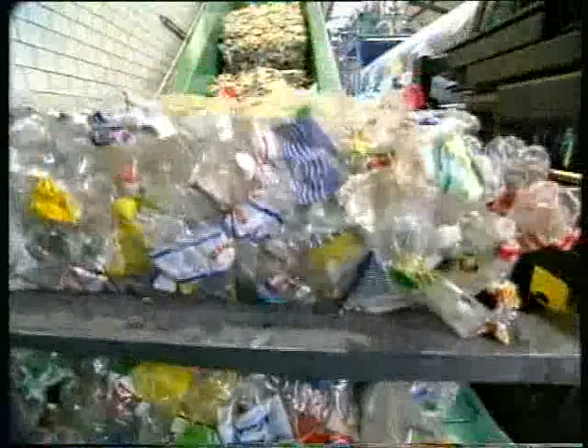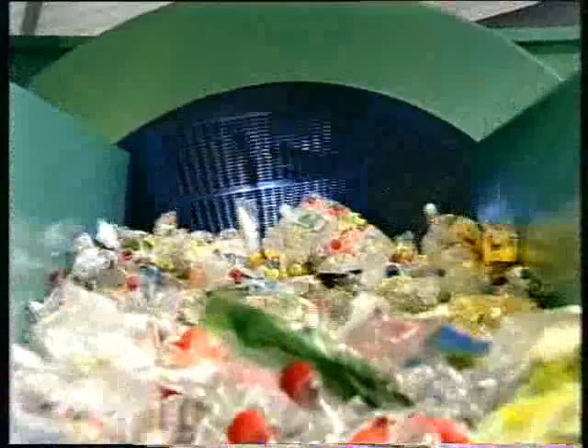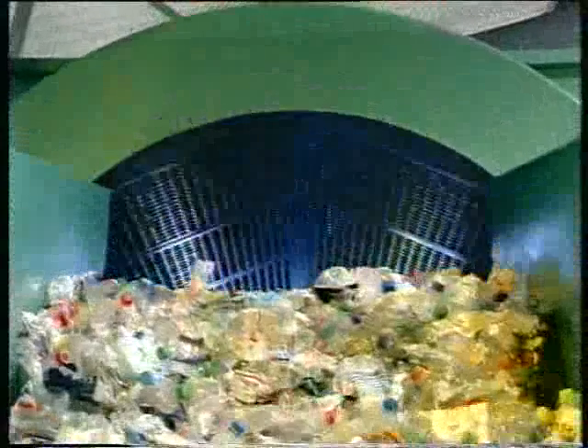This plastic, which is on the advance for beverage packaging, can be recycled as often as desired as long as it's properly sorted and prepared. In the separating drum, the bottles are cleaned and the metal parts removed with a magnet. Then the bottles are ground. A blower removes most of the label fragments. The polyolefins, from which the bottle tops are manufactured, are separated out using the sink-float process.